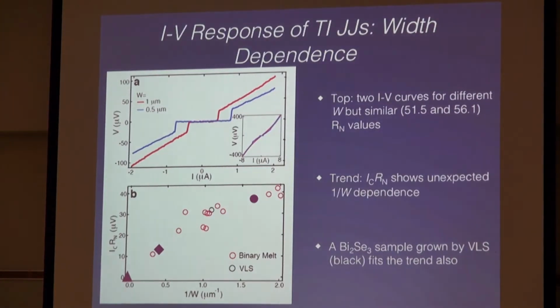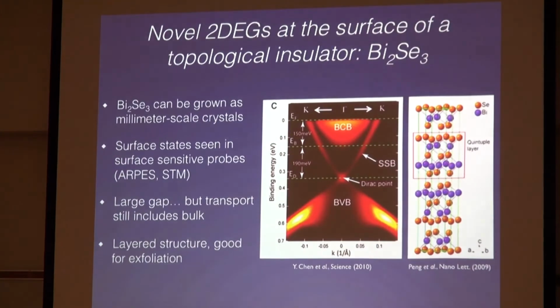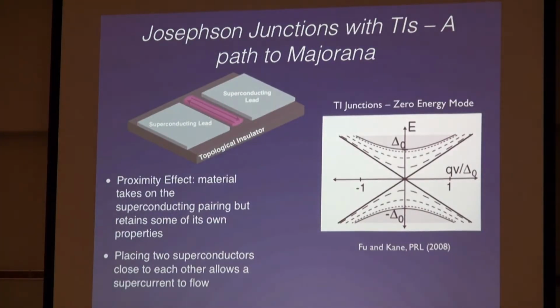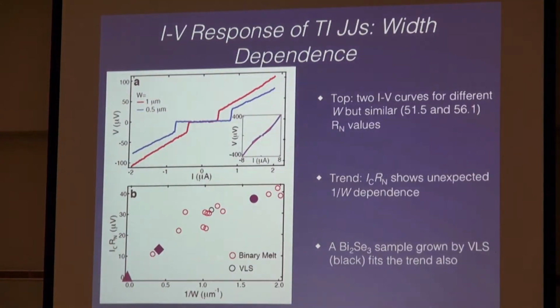Okay, so we make these devices. I thought I had a picture of them somewhere. Don't. These devices aren't easy to make. You actually have to put these two superconducting leads quite close together to induce the topological superconductivity in this region, and then measure a supercurrent. You have to get this to be 20, 30 nanometers apart, which we can do. And when you do that, you measure something that looks like this.